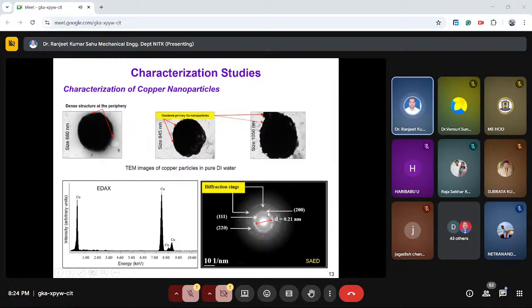Similarly, the lattice spacing for the next two rings was found to be 0.18 nanometer for the 200 plane and 0.128 nanometer for the 220 plane. This also matched the FCC crystalline lattice distances of 0.18 and 0.128 nanometer for the 200 and 220 planes respectively, as per the JCPDS database. Okay.